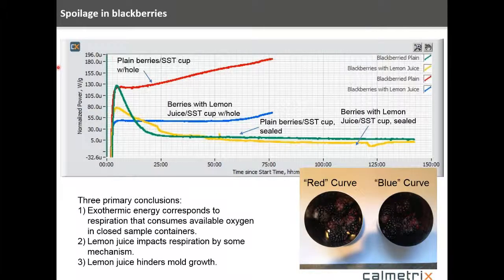So here's an example of that. This happens to be in an example using blackberries. Again, there's a lot of data here, so let me walk you through the progression. The first run here are plain blackberries that were run in a stainless steel cup with a hole in the top of that cup. So it was basically open to the environment, so there was plenty of air getting into the sample. And you can see there's exothermic activity, and it continues to advance as time goes on. Normally with blackberries, the respiration would fall off as a function of time, but the fact that heat flow continues to go up means there's other things going on. And in fact, when you look at the sample after the run, there was obviously mold growing, so there were other things that were happening in the sample.